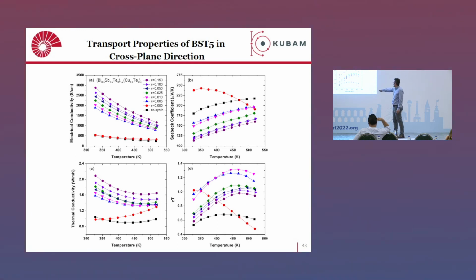So this is our typical BST5, with no additions. This red one is the one we made with 10 minutes of ball milling, and the others are 10 minutes of ball milling plus the copper telluride addition. At low temperature, our best material is comparable with the 10-minute ball milled material, but at slightly higher temperature, like 450K, it outperforms. We reach a ZT of around 1.3. It is quite an important improvement for this material.